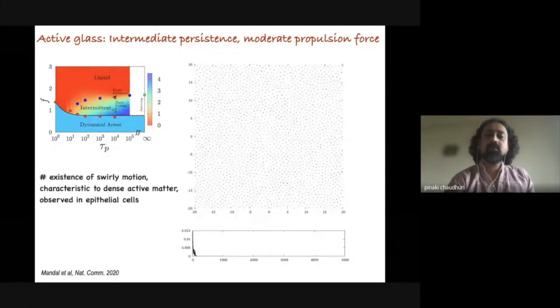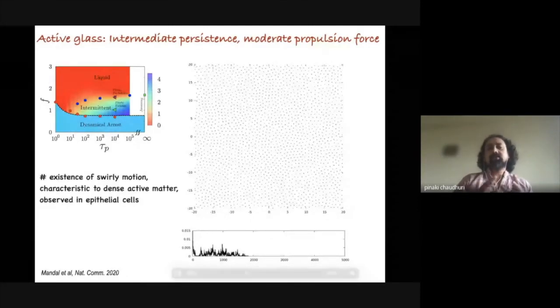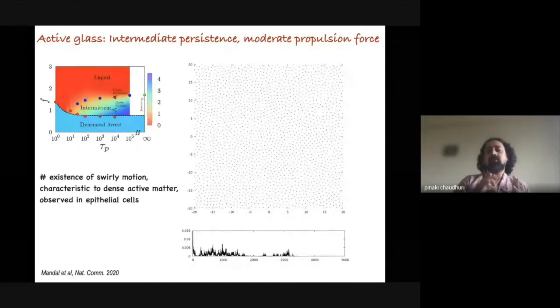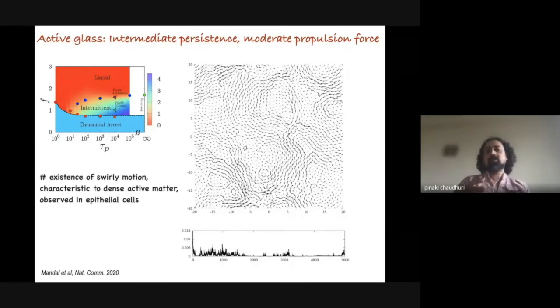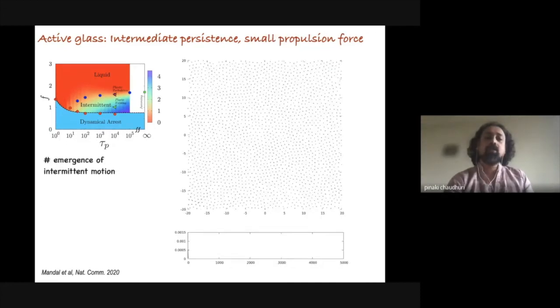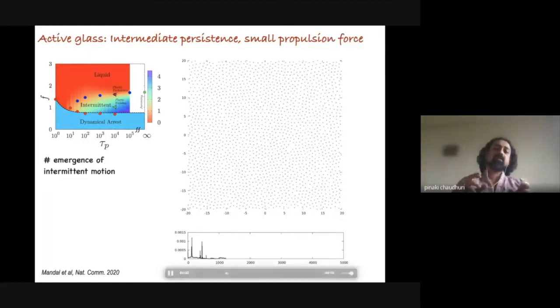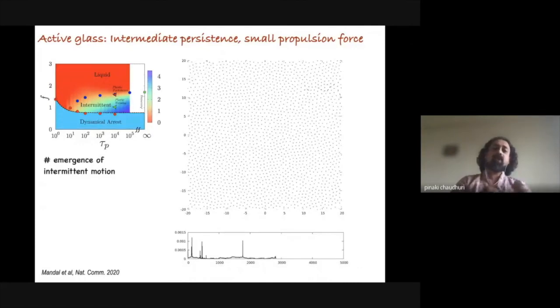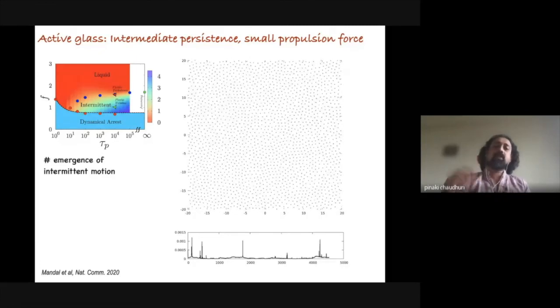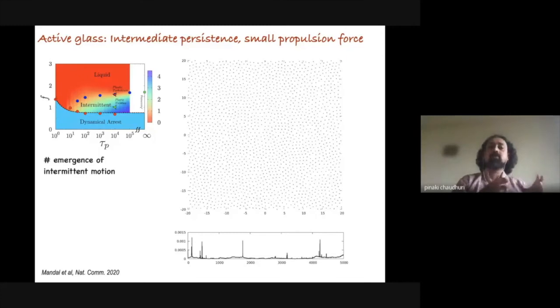If I'm in some regime somewhere around here, I see very swirly motions happening whenever some local event occurs. So bursts of swirly structures emerge. This kind of swirly motion is actually observed in real active cells, for example epithelial cells, and that's why it has also given rise to using glassy ideas in these biological systems. On the other hand, if I go to smaller and smaller active forcing, one sees very intermittent bursts, like plastic events. So if I tune this active forcing, I can go from a liquid-like behavior to a region with swirly motion, and another region with very intermittent dynamics. There's a huge and rich phase diagram that one can explore, and this is work in progress.